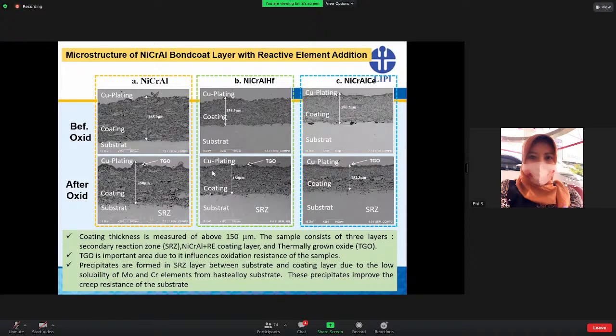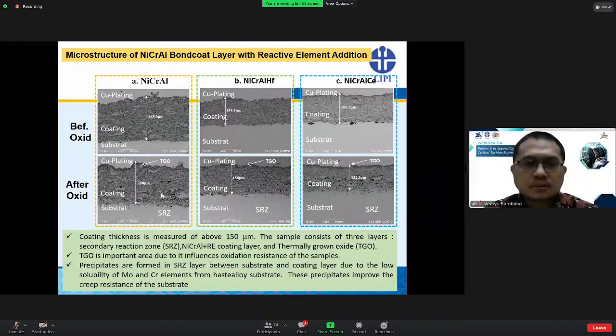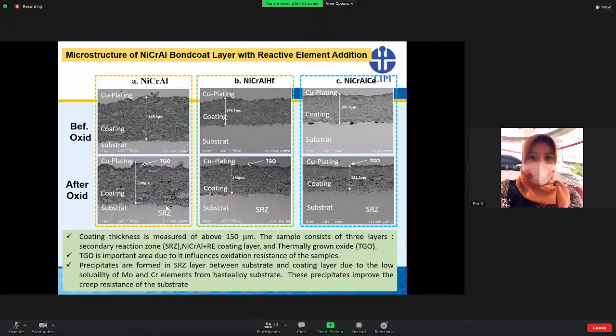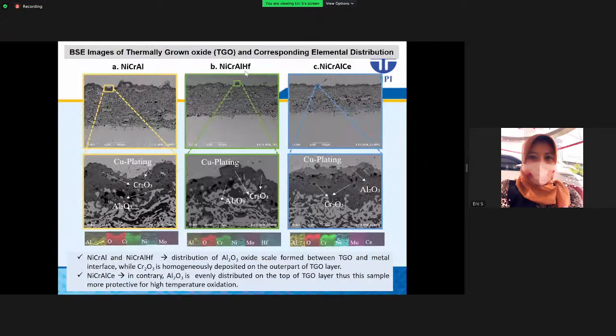After the oxidation, the sample consists of 3 layers: secondary reaction zones, coating layer, and thermally grown oxide, which helps to keep the other layers. And in order to clarify the TGO layer, a high magnification was selected from the selected area here. The nickel, chromium, aluminum with the addition of hafnium looks to have a similar structure.